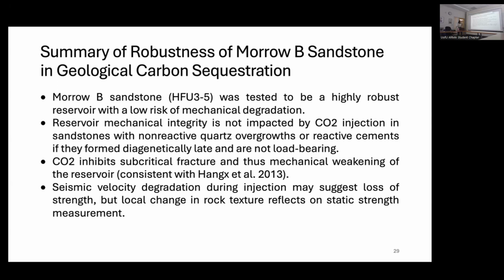And that finding is consistent with the previous study. And last, the seismic velocity degradation during the injection may suggest loss of strength, but shouldn't be an indicator of how much the reservoir has been weakened. So we should focus on the local change in rock texture, which you can tell by looking at the static strength measurements, like tensile strength, uniaxial compressive strength, or the static Young's modulus measurements.